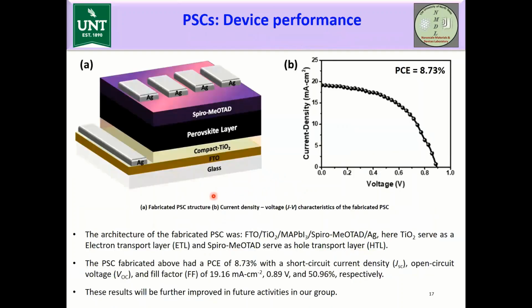The structure of the cell that we are making is NIP type, which includes FTO, compact TiO2, the perovskite layer, a Spiro-MeOTAD layer, and the top contact, which is silver in our case. So TiO2 and Spiro layers are used as electron transport and hole transport layers respectively. So far the cell which achieved the highest efficiency in our lab has a PCE of around 8.73%.